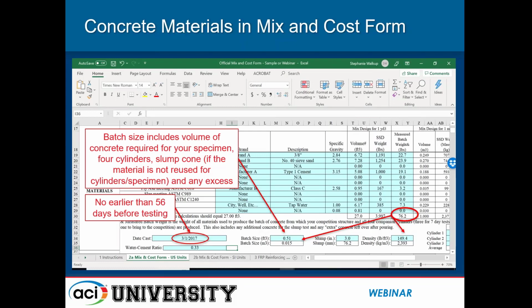The batch size includes the volume of the concrete required, again, for not only your specimen itself, but also for 4 cylinders and a slump cone if the material in the slump cone is not reused for your cylinders, as well as any excess material that you need to batch the concrete. So the batch size is not just the size or volume of the member itself. If it is just the volume of the member itself, it's an indication or a flag to someone on the review that the mix and cost form is not filled out appropriately. In addition, the date of cast needs to be no earlier than 56 days prior to the testing day.